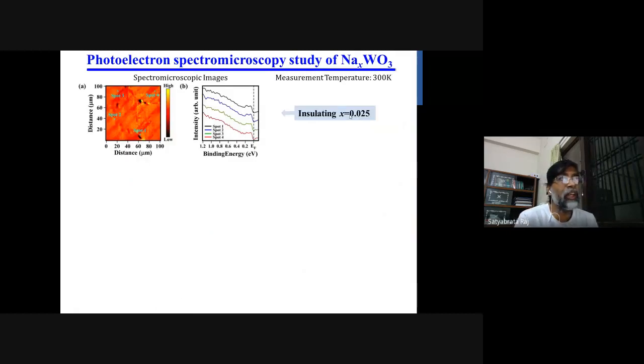In an insulating sample, we have taken data at different spots, and in every spot the spectrum is the same, but the mapping shows different yellow and red types of patches. These are artifacts of the spectra. That means the spectrum is not well focused in the red zone, whereas it is well focused in the yellow zone. Because when we clean the surface, actually we don't clean, we fracture the sample, and the fractured sample is not very flat, though it is clean and some steps are there.